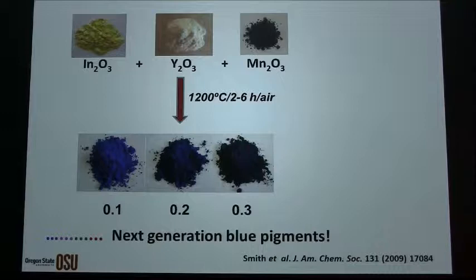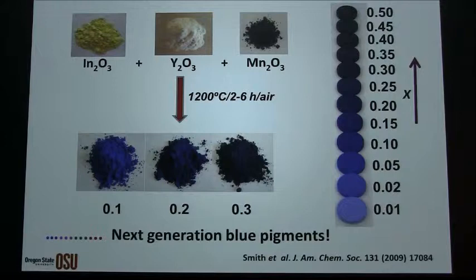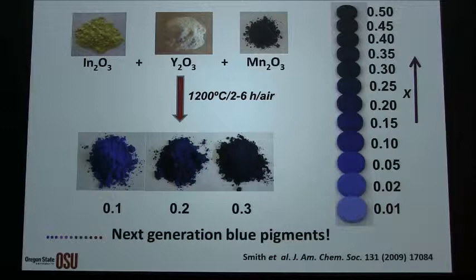In fact, one of the reasons why these pigments have become so popular is because we can actually change the color of the pigment by simply changing the ratio of the manganese and indium in the crystal structure. So you can actually go from a very light blue to a very dark blue to nearly black by simply changing the manganese to indium ratio in the starting material of these compounds.